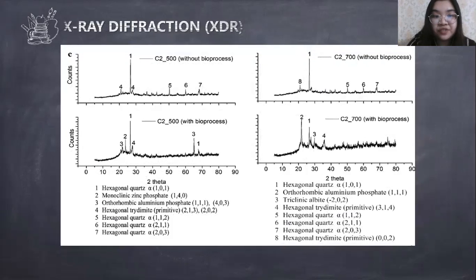C and D are for sugarcane bagasse. In both of them, the crystalline phase present is quartz. The only difference is that not all the diffraction planes are the same as for 500 degrees Celsius. Aluminum phosphate appears, while albite appears in 700 degrees Celsius. And by that, we assume that the calcination temperature and earthworm metabolism have a huge role in generating different crystalline phases, not only silicon and oxygen, but also other elements. Also, the silica shows several polymorphs depending on temperature and pressure.